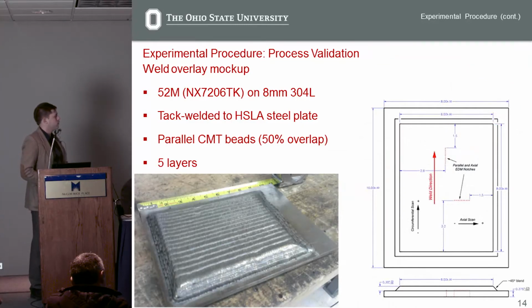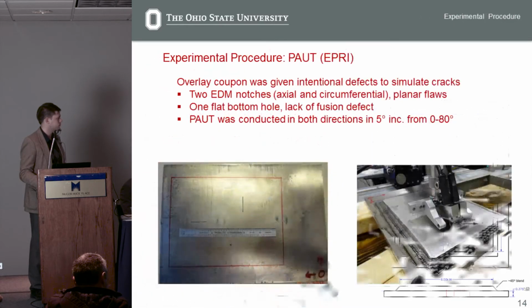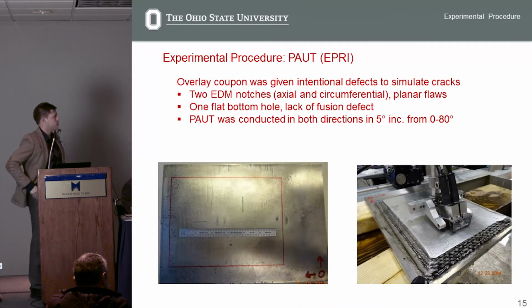The weld overlay mockup was designed from EPRI's requirements for a phase array ultrasonic test coupon, which was the top 6 inches by 8 inches of overlay weld metal, and it was done with 5 layers to make a buildup of at least ½ inch. Phase array ultrasonic testing was performed at EPRI, and the overlay coupon was given two intentional defects to simulate cracks and flat bottom holes in both the axial and circumferential direction. And the phase array test was conducted in 5-degree increments from 0 to 80 degrees.